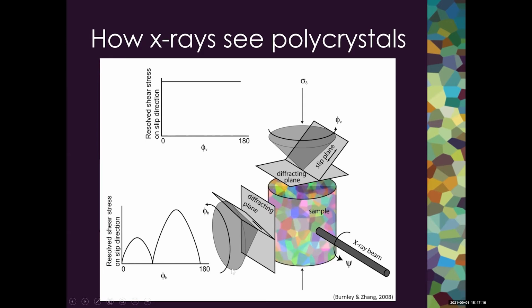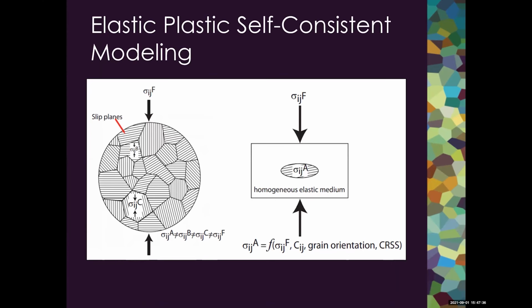And so the complexity of this diffraction data requires an interpretation technique that can make the maximum use of this data. And so as I'll discuss next, when we forward model our diffraction data, we tend to focus on the modeling of the diffraction data from detectors in the compression direction, as our data is typically much cleaner. And so elastic plastic self-consistent modeling provides us with the ability to analyze data at a level more comparable to the complexity of our diffraction data.